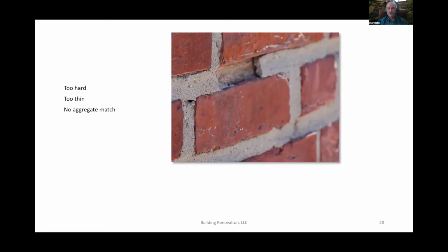So here is a mortar that the contractor put in that is too thin, it's too hard, and there's no match. They're using mason sand here, and you can see the stones in the background are much larger. And this is a very hard mortar. These brick faces on other locations on this building are popping off now because it can't move, it can't let any moisture in. In a common brick, and around this neighborhood, I'm originally from Buffalo, New York, but around here they call it Chicago Commons.